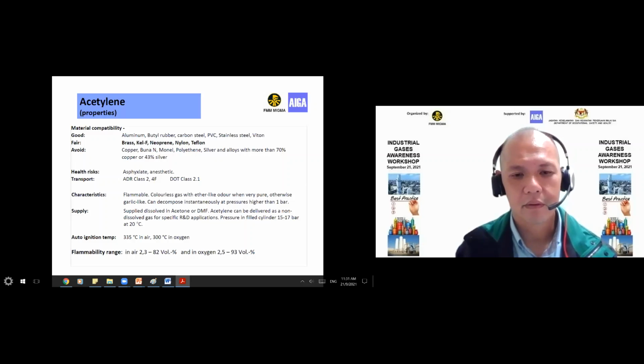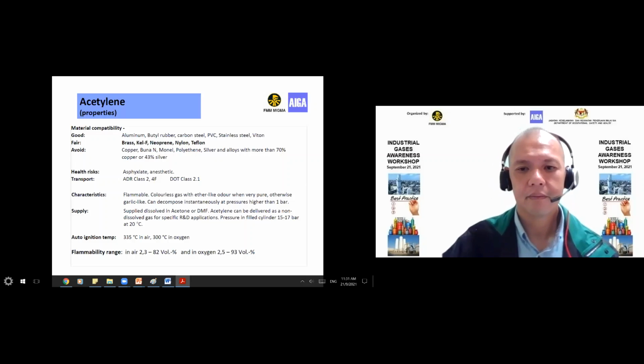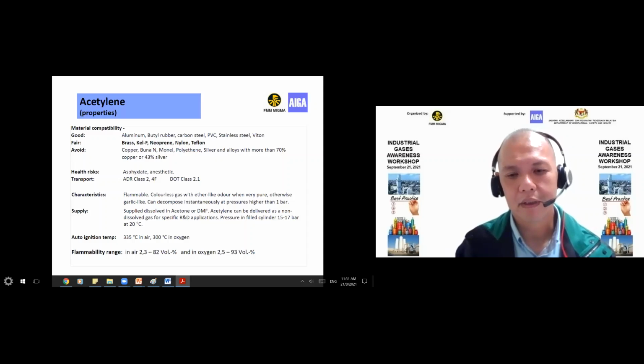And of course, as I have been repeating, acetylene is supplied dissolved in acetone or DMF, right? Normally the acetylene cylinder pressure will be in the range of 15 to 17 bar at the reference temperature of 20 degrees Celsius. The auto-ignition temperature for acetylene in air is 335 degrees Celsius. In an oxygen-enriched environment, the auto-ignition temperature drops down to 300 degrees Celsius.